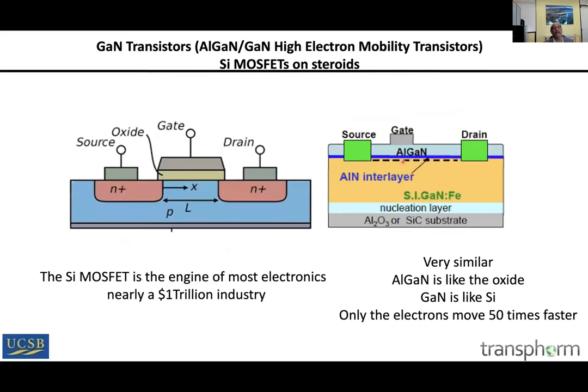So what is the basic device that we use? We use an AlGaN-GaN HEMT. An AlGaN-GaN HEMT is gallium nitride grown on foreign materials, aluminum oxide, silicon or silicon carbide. And then you have AlGaN on top of GaN. At this interface, you have a two-dimensional electron gas. This is a very thin sheet of electrons that carries current.